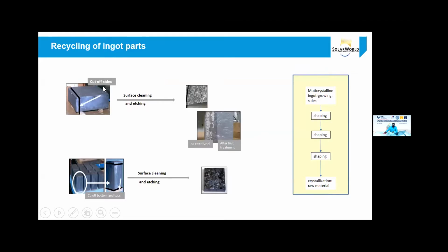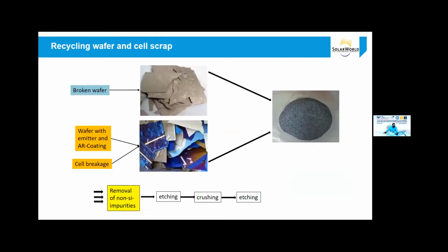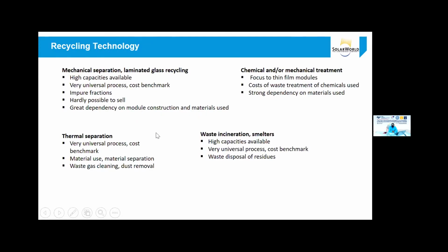How can solar panel recycling handle ingot parts? What they did was surface cleaning, first surface cleaning and etching by chemical, so the surface can be prepared for reuse. This is the Solar World recycling process. For recycling wafer and cell scrap, broken wafers, and wafers with emitter and anti-reflective coating, they remove the coating and use hydrochloric acid and other chemicals for etching and purifying it. And this is the pure silicon powder, so they use it to produce a new solar module.